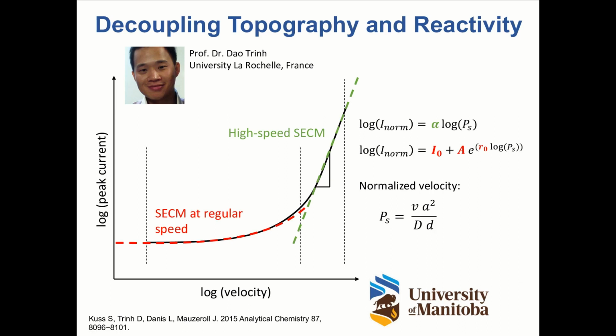So in this model, there are 2 ways to extract a numerical value for the substrate kinetics. Here we are calling the substrate kinetics the apparent heterogeneous rate constant. We can do this in 2 different ways: at high scan rate, high scan speed SECM, or at regular speed SECM. High scan rate means anything above 100 micrometers per second. We like to normalize the velocity in the way you see in this equation, where V is the velocity, A is the radius of the active area of the microelectrode, D is the diffusion coefficient, and the small d is the tip to substrate distance.